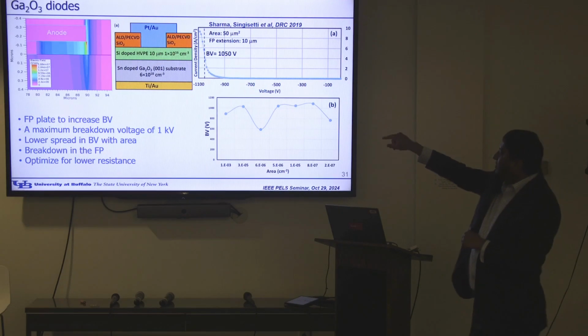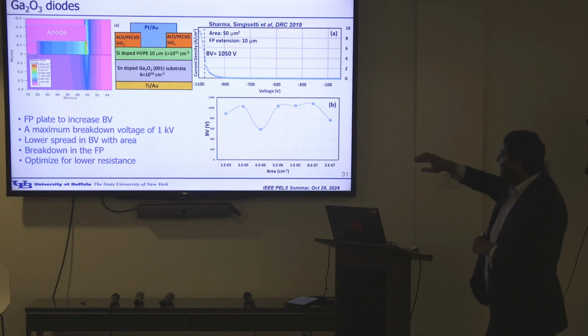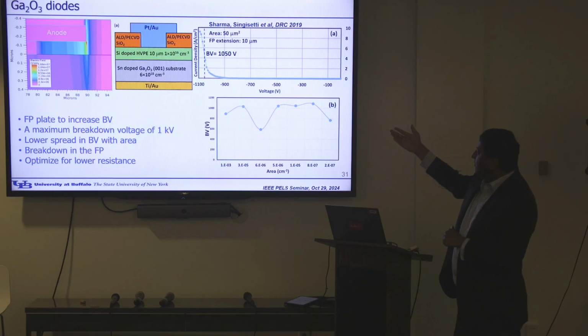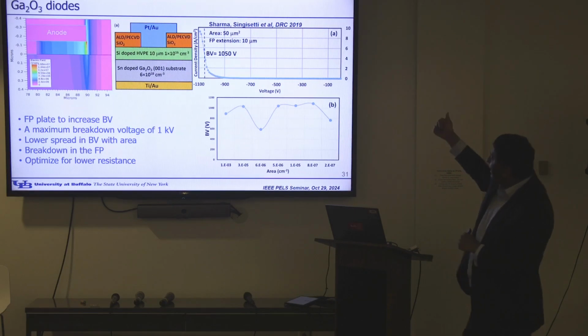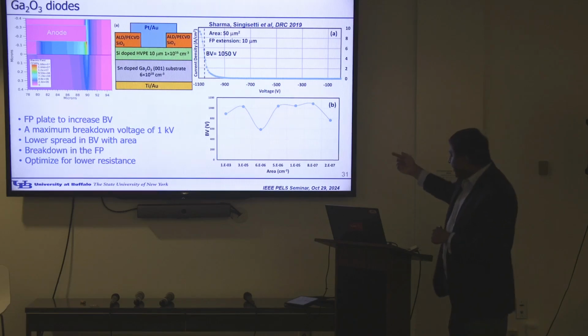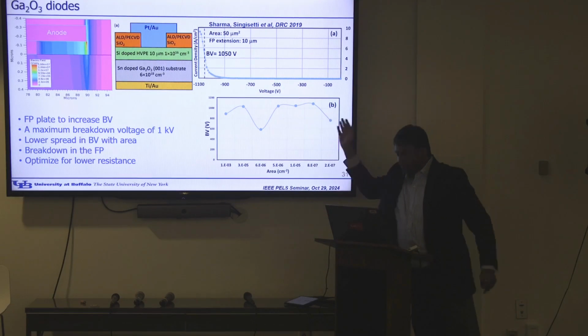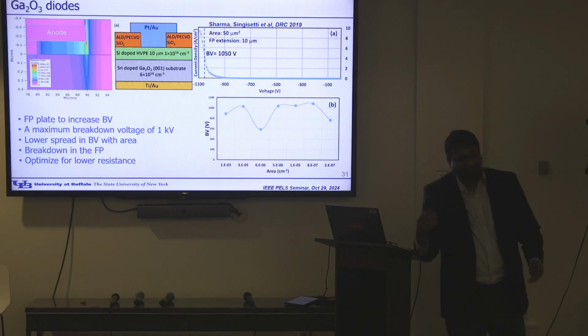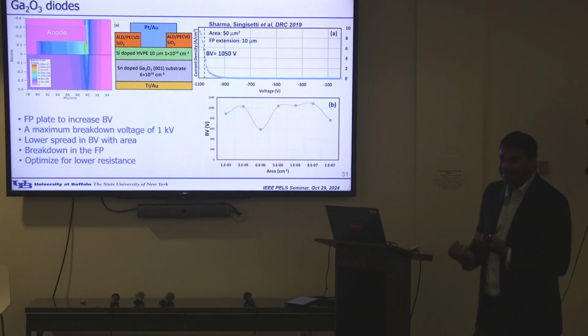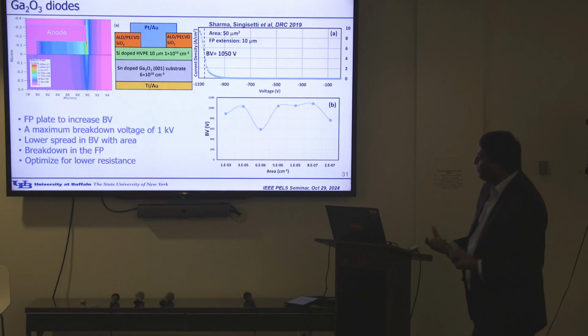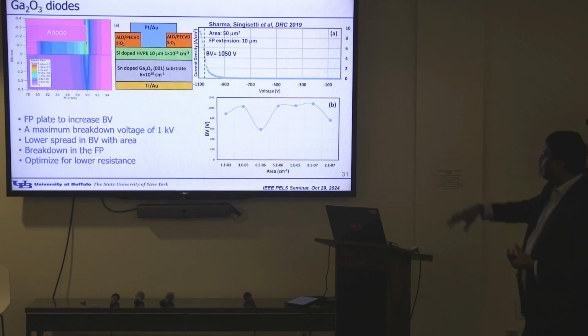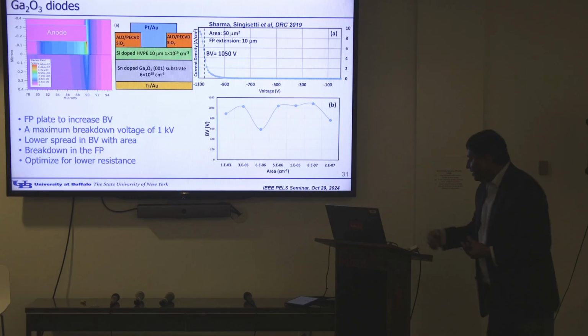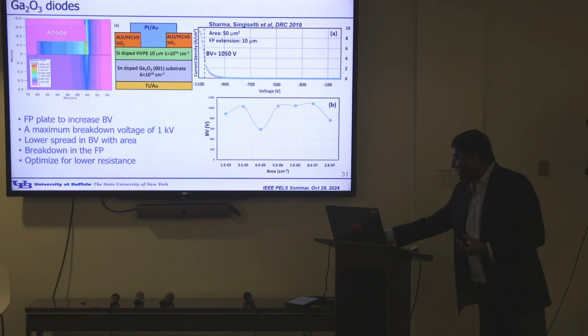So this is a diode. It's a standard field plate design again. Nothing too fancy here. We were able to get one kilovolt. This was 2019, pretty early, and also the 1 kilovolt without any dependence on the area. Typically, when you say very new technology, there's always variation in the size of the device. The breakdown is lower for a large area versus a small area. You can see that it is more consistent here. People have made rapid progress in the, as I will show later.